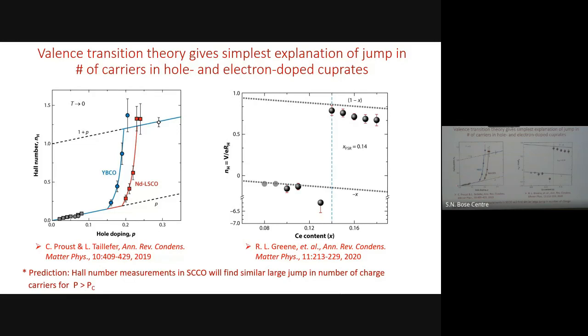In hole-doped materials, as you dope it, the number of carriers is linear with the number of doped holes. At a certain point, it suddenly jumps. There are more recent references, and it becomes 1 plus P. I am saying this with complete faith, and trust me, there is no explanation of this. There is suddenly a large jump in carriers. Most interestingly, you see that in the number of carriers in the electron dome. It's flat and then it jumps. No explanation for this. If you think of what I'm saying, that is all given by this equation.